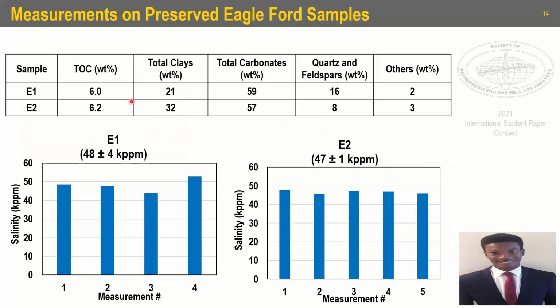Now, in this slide, we do these measurements on preserved Eagle Ford samples coming from the same formation, but separated by 50 feet in depth. We pretty much see here that they have comparable petrophysical parameters: the TOC is close to each other, and the carbonates and quartz and feldspar contents are close to each other. For the various measurements done on these samples, we're able to predict that the salinity for this E1 sample was 48,000 plus or minus 4,000 ppm, and for the E2 sample was 47,000 plus or minus 1,000 ppm.